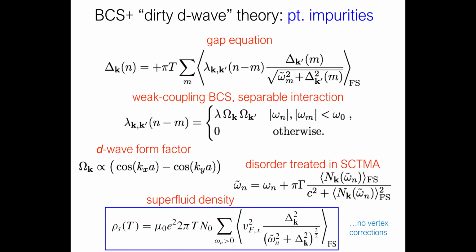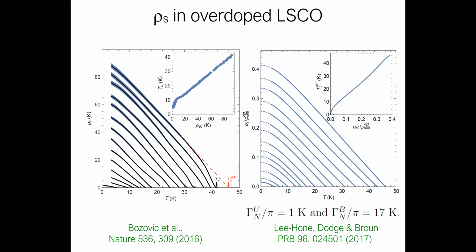So I'm not doing anything very fancy or new here, but if you do that and you go back, you can find a set of impurity parameters which allow you to fit the data very well. It gives you not only the scaling of TC with rho S naught, but it predicts that maybe at low temperatures there should be some curvature. It's hard to see because Ivan, for these samples, didn't measure low enough. There are definitely deviations at the very lowest TC samples, and I can come back to that and comment on that if anybody's interested.